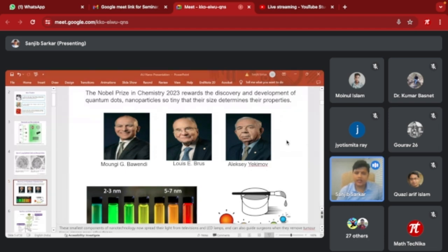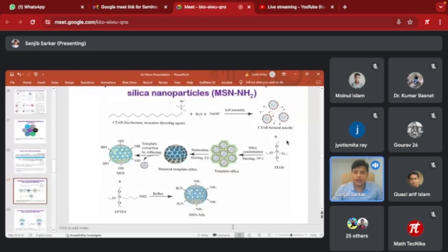So silica nanoparticles are already approved in several forms, like Cornell dots. This is a silica sphere, not a mesoporous silica nanoparticle. This is a silica sphere which was approved several years ago by the FDA, and amorphous silica is also approved by the FDA. Now, in our laboratory, we synthesize mesoporous silica nanoparticles using the molecule TEOS, tetraethyl orthosilicate, and the surfactant is CTAB. By this surfactant, we form the structure of the nanoparticle, and actually it forms the pores of the nanoparticles. Finally, after refluxing, the pores are created and this spherical nanoparticle is made.